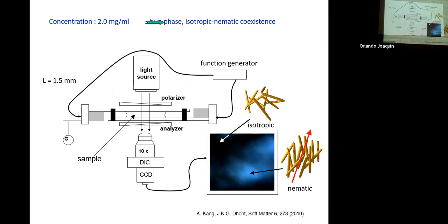So the stripes you see are bundles of the virus. So, for example, this is a domain where the rods are nematic. We have the director alignment. And because they're birefringent, the refractive index along the rod and perpendicular to the rod are different. So it will rotate the light.